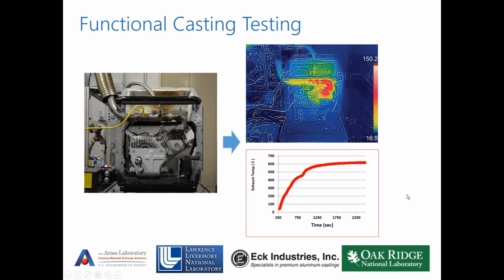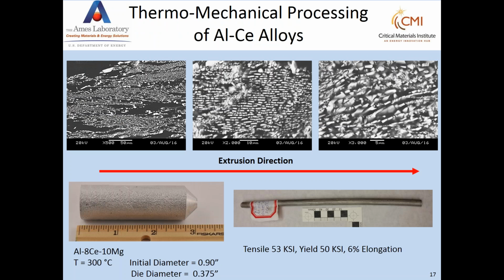There's work going on with our conventional customer base in these alloys in projects of their own that we're looking to participate in. One of the very interesting things, at least to the team, is that when you process these alloys, when you take a typical cast piece of the 8 cerium 10 mag alloy and you extrude it and you align all the aluminum cerium, or at least most of the aluminum cerium, you get very, very high mechanical properties. And again, this is except for the temperature that went into the extrusion billet in order to allow it to extrude. It had tensile strengths in excess of 50 KSI with a 6% elongation in the extruded alloy.